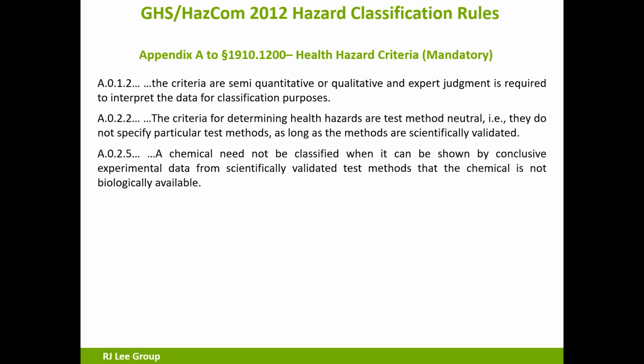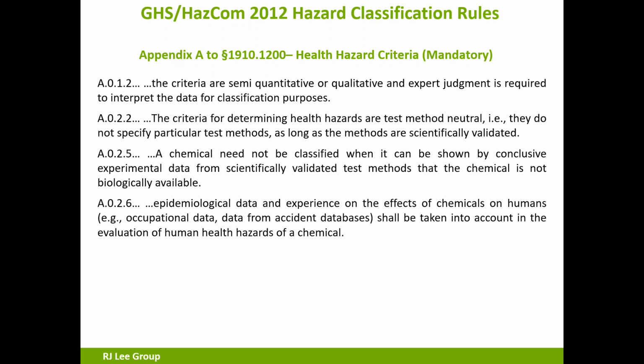A chemical need not be classified when it can be shown by conclusive experimental data from scientifically validated test methods that the chemical is not biologically available. There is that biologically available again. Critical: epidemiological data and experience on the effects of chemicals on humans shall be taken into account in the evaluation. This is very important. If you've got a product that you've worked with for 30 years that is supposedly hazardous, and yet you have a good medical management program, a good comp program, you track everybody's health, you know everybody's been healthy, and no one has ever reported a problem with that chemical, whether it be a corrosive, a sensitizer, whatever it may be, our epidemiologist can come in, pull that data, and you can get a non-hazardous classification based on epidemiological data.